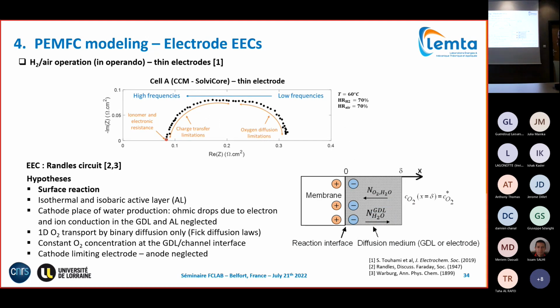Okay, but normally you use your fuel cells not to store charges, but to convert hydrogen and oxygen into water and to produce electricity. So the typical configuration is an operation with hydrogen and normally air. The typical spectrum we measured is shown here, two half loops. Remember, low frequency oxygen diffusion, intermediate frequency charge transfer kinetics during the oxygen reduction reaction inside the cathode, and the highest frequency intersect with the real axis associated majorly to ion conduction through the ionomer. And the typical circuit used is the Randles circuit.